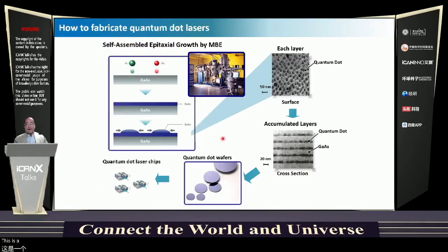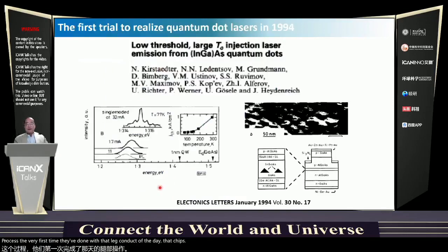This is just to illustrate how to fabricate the quantum dot lasers. We grow quantum dot structures. Each layer has a high density of quantum dots, and we stack the quantum dots by molecular beam epitaxy. And then we finally process the wafers, and we get the quantum dot laser chips. Since then, many groups have started to work on these self-assembled quantum dots.